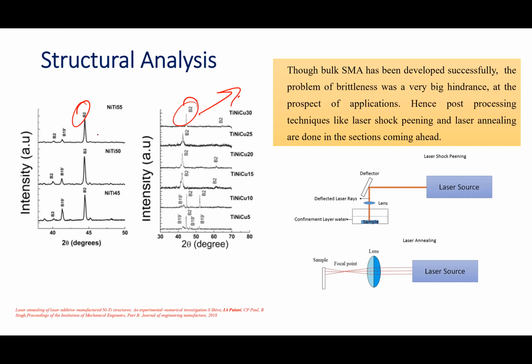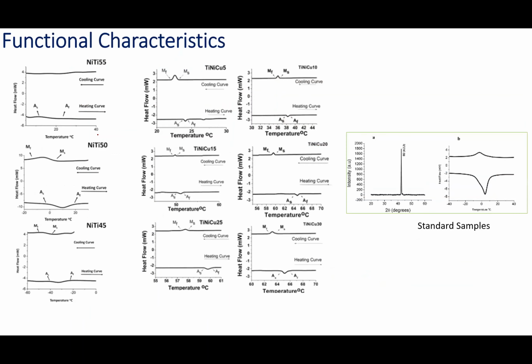So what we thought is we will go for some kind of post-processing. Since we have a laser in mind, we thought we will go for laser-based post-processing. One technique we employed is laser-based peening, and the other technique we employed is laser-based annealing. With laser-based annealing, we thought we could eradicate the amorphization and also relieve the stresses. In the case of laser peening, we try to induce uniform stresses along the surface to get a proper structure. This comparison basically gives us clarity.